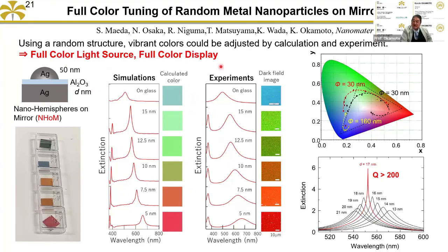That's the simulation and that's the experiment, and that's my sample color. By using only this method, the three elemental colors are reproduced, and a very sharp resonance peak with a quality factor of 200 is also available. Controlling the thickness is very easy, just by controlling the evaporation time. Then this structure must be useful for a full color light source or full color display.